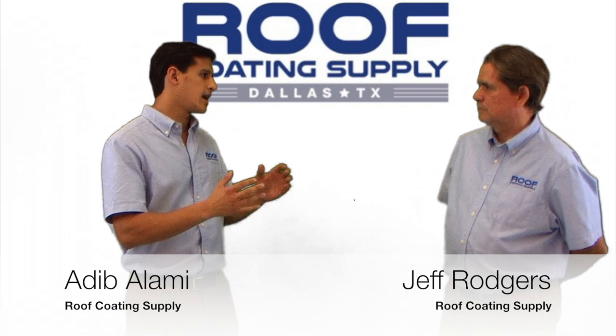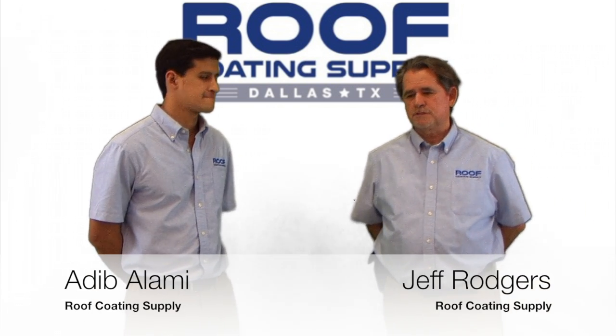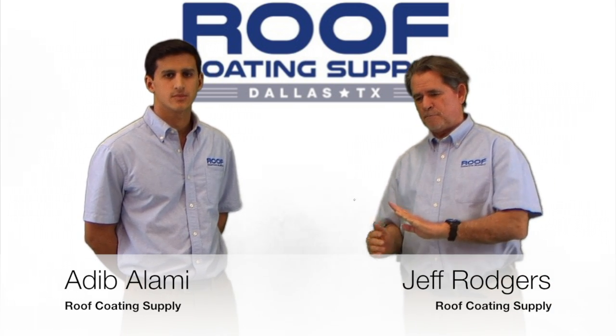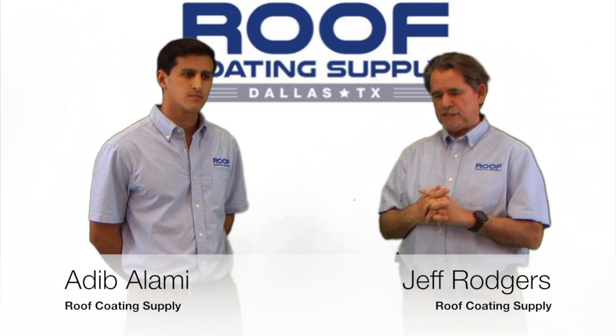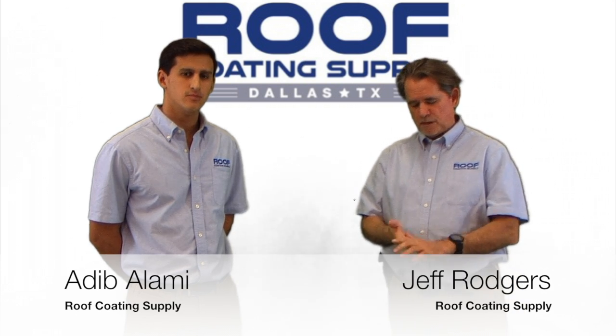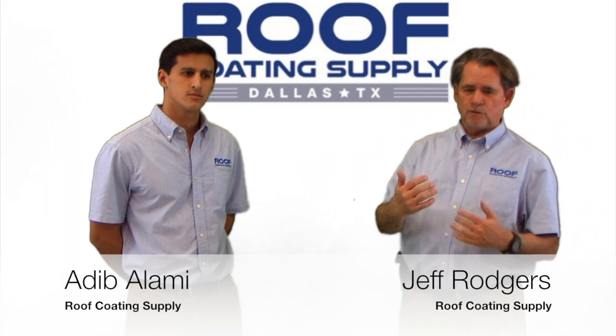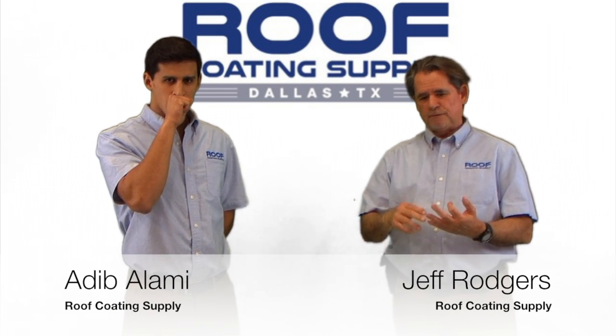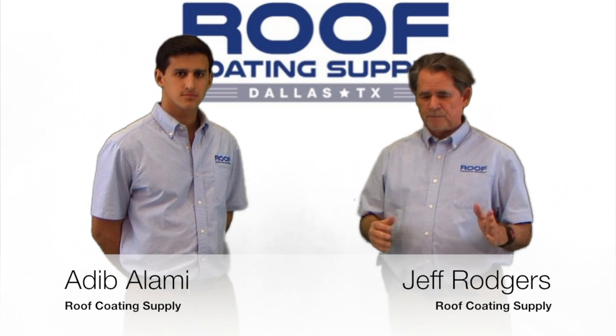If you were to install one of these systems, how would you install them? Well, most of your built-up roof systems come from kettle asphalt that is heated in the kettle and that heat pumps it up to the roof. Typically, you would put down a base sheet over your ISO or whatever your decking is, whatever your substructure is, and then over that you would begin to mop — a process of unrolling different qualities of base sheets and mid-ply sheets, all primarily asphalt-coated fiberglass products that come in rolls.